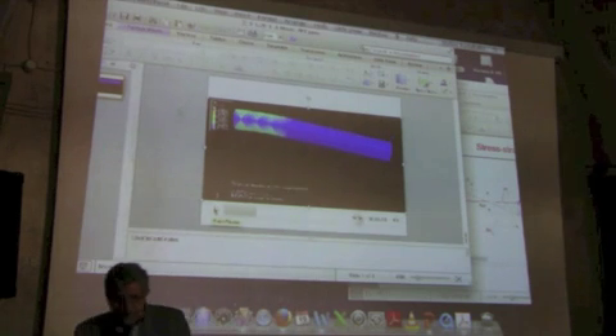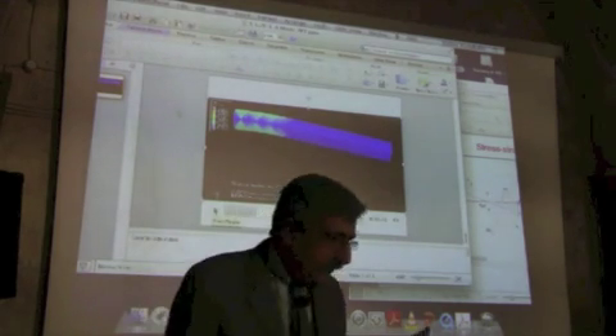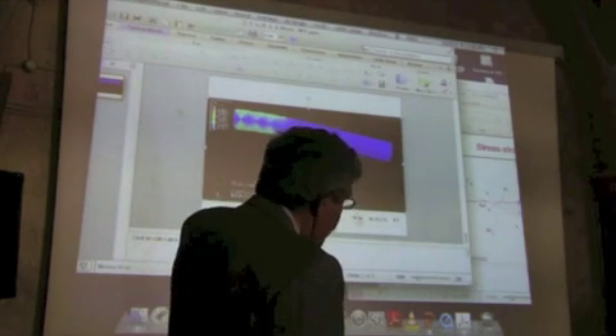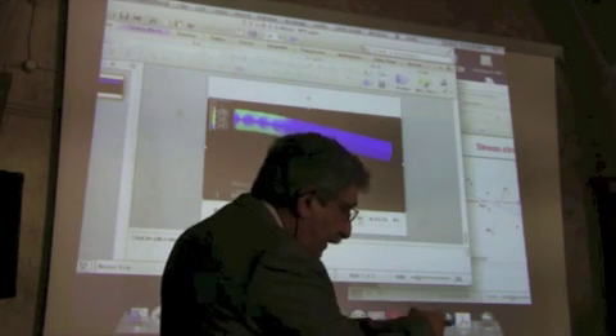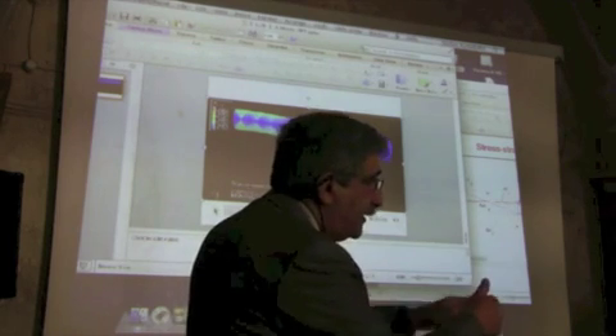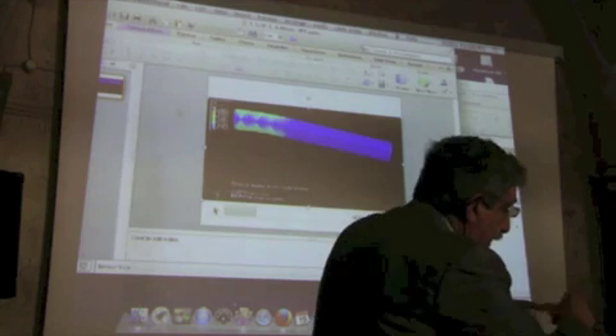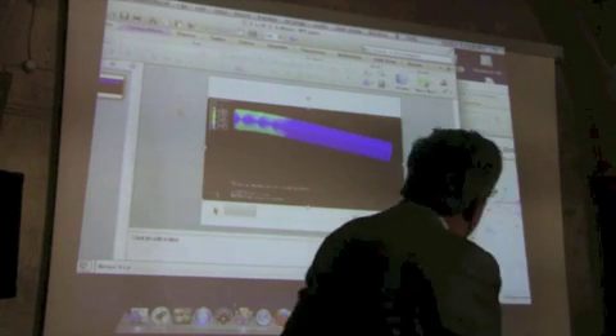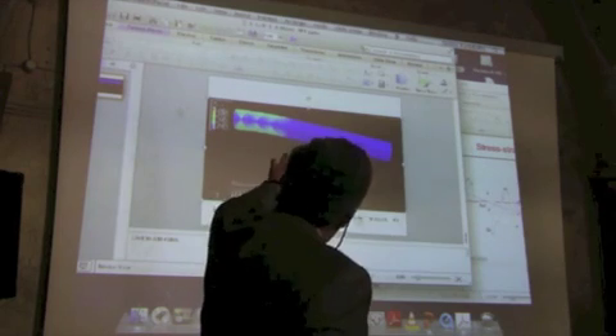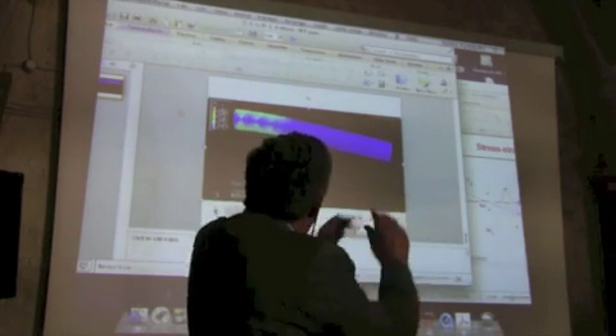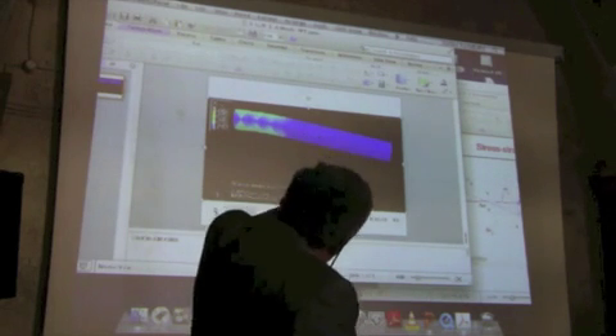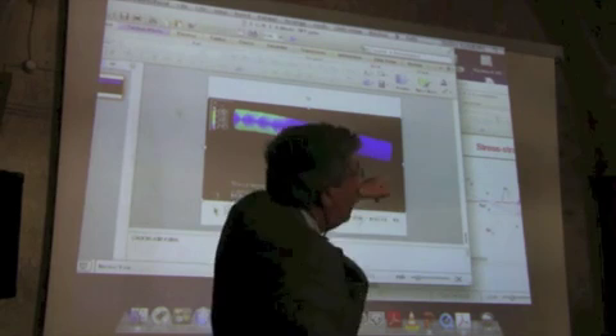So, the bright color is Luders bands forming, but they are forming in a particular way. They're bands that are happening on the tension and compression sides. They're kind of like this on top, and they're propagating in this fashion. Behind, the tube is ovalizing, and it is also wrinkling. It has higher curvature over the green, and blue is lower curvature.